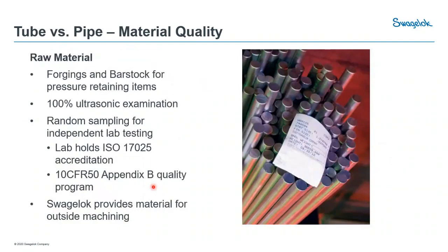So beyond just having those chromium and nickel levels, it all starts with the raw material. So we talked about the performance of the fitting itself, but there's a lot that goes into the material and the feedstock into your component. So for one, all forgings and bar stocks are used for pressure bearing and pressure retaining components. We do 100% ultrasonic examination, we do eddy current analysis, and we always do random sampling. So we have an independent lab, and our lab holds ISO 17025 accreditation. And many of our components have nuclear requirement as well. So 10 CFR 50 Appendix B quality program, which really holds our material to a high standard.